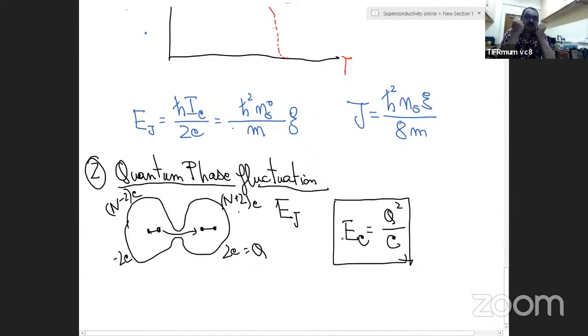On the other hand, if the Coulomb energy cost is very low, if your islands are very large, in that case, the exchange of particles will happen much more efficiently. And when the exchange of particles happens much more efficiently, the phase will get steeper. So the phase fluctuation will reduce. This concept is what is embedded in superconductivity.